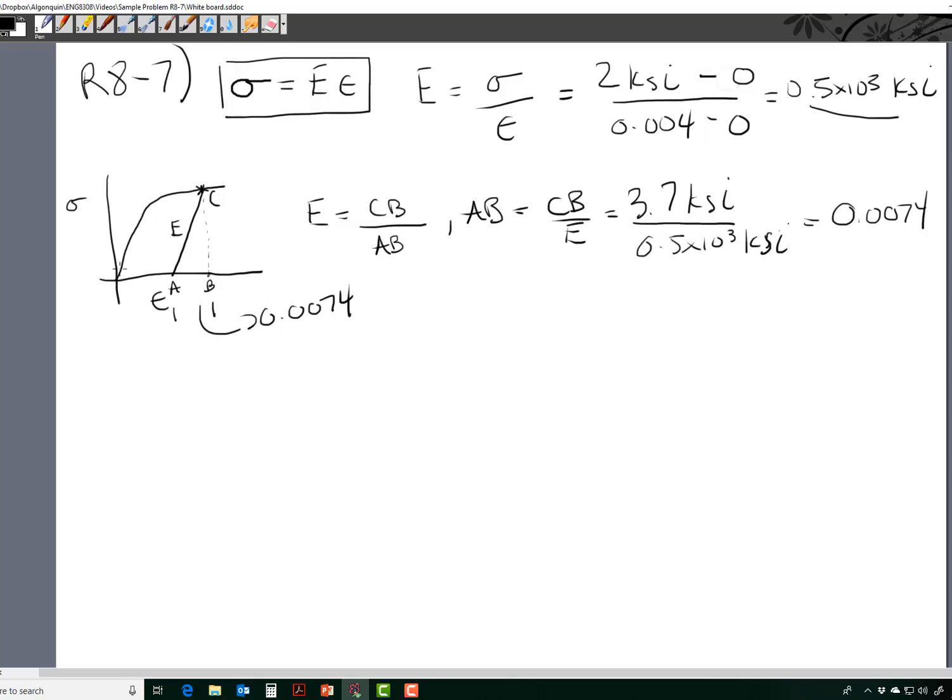So recall this sample is going to go up, it's going to get into its nonlinear response or plastic region, but when we unload it, it's going to come back parallel to the initial young linear response of the material. So we've just said that this here is 0.0074, so the material is going to come back to this point right here.